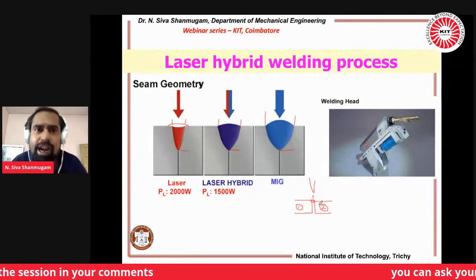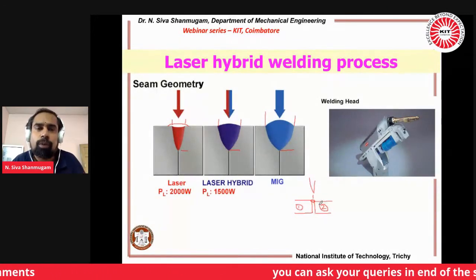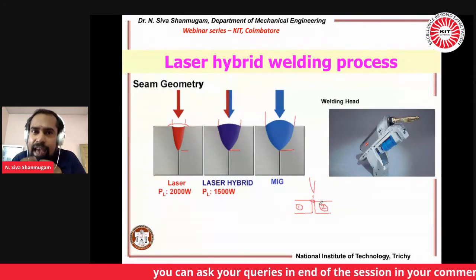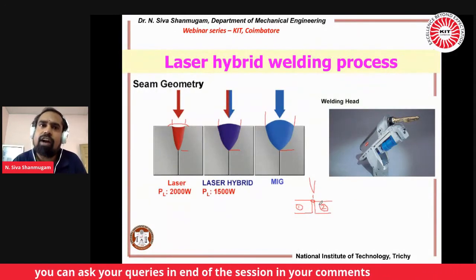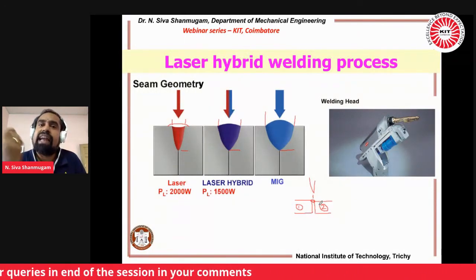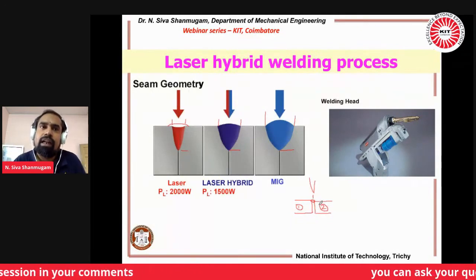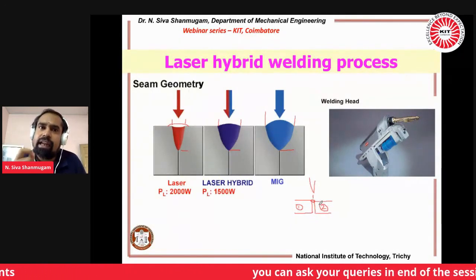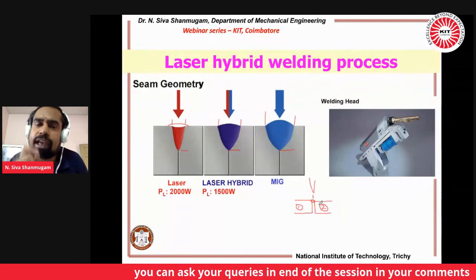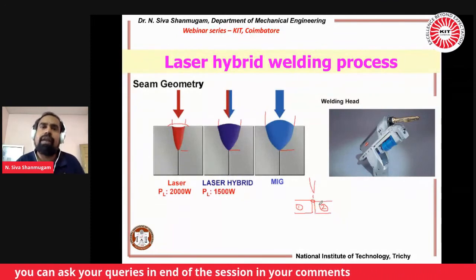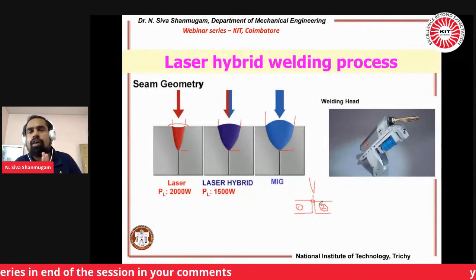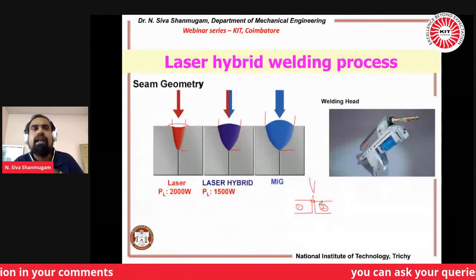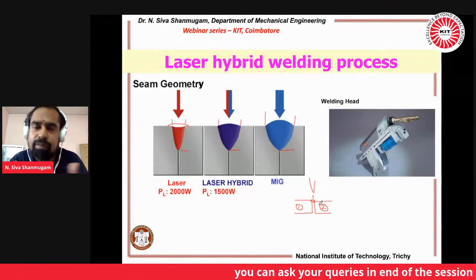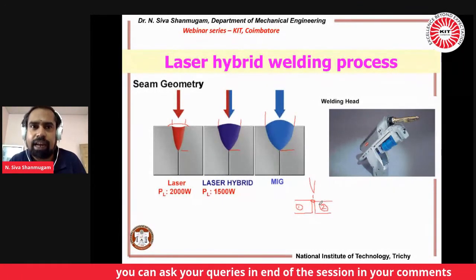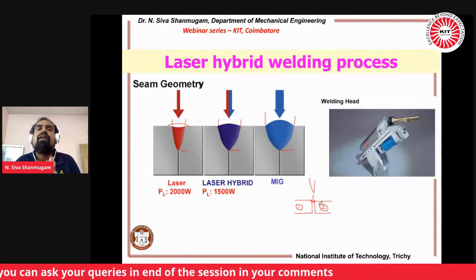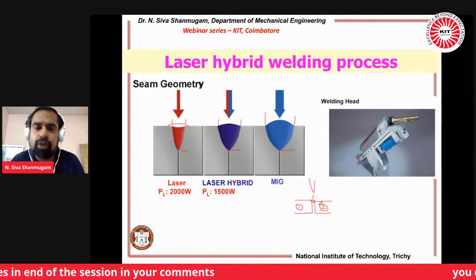To avoid that, sir, I am not supposed to maintain a gap, because the main drawback of laser beam welding is the need for airtight tightness between the two sheet metals. The tightness should be maintained within 40 microns. If it is more than 40 microns, your laser will not penetrate the material. Instead, the entire energy will be wasted in between the gaps. So airtight preparation is required to do the welding.